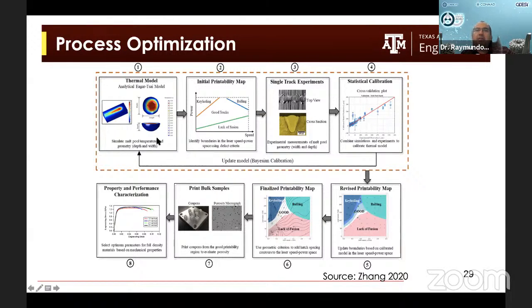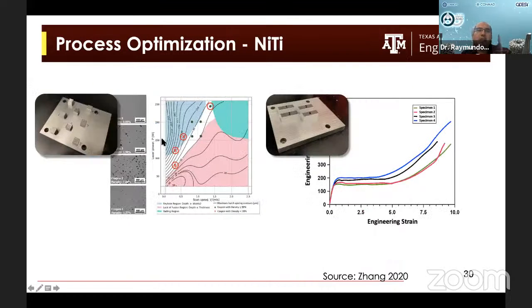So we have a thermal model, we predict an initial printability map, we carry out single track experiments, we calibrate the models. Now that we have models that are calibrated, we revise the printability map, right? To figure out where are the regions where you are more prone to keyholing or lack of fusion or balling in the case of powder bed fusion. And then we print, this white region is the good region. We print parts in this good region, and then we carry out characterization of the printed tensile specimens. In the case of nickel titanium, this is how it works.